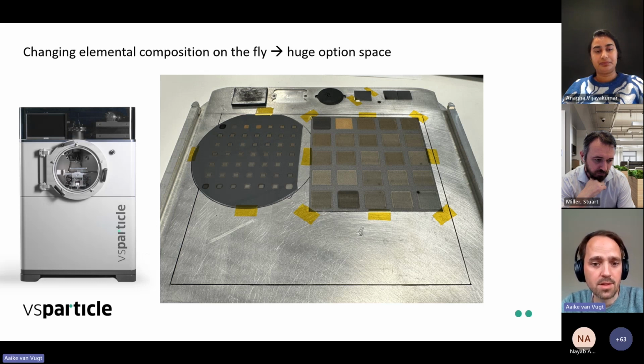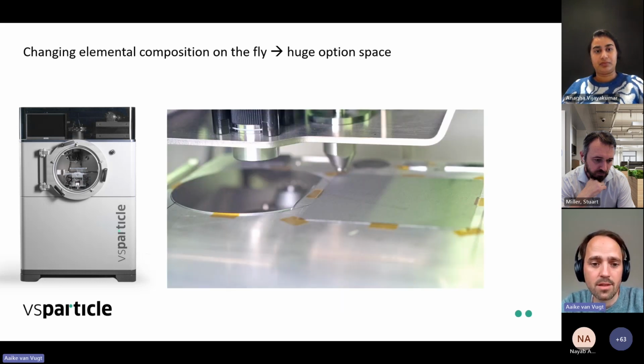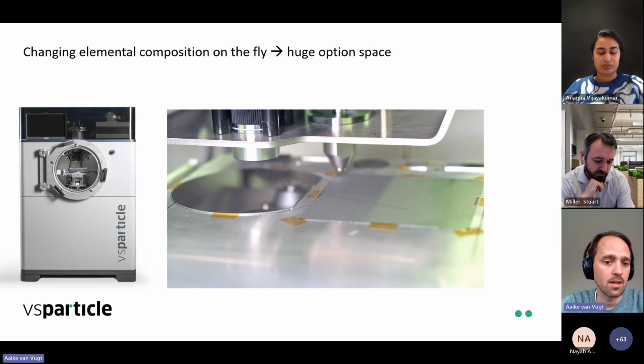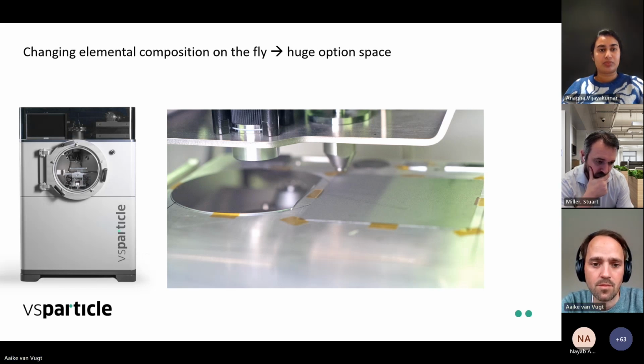And to give you a bit of perspective on how the system looks if it's printing these samples, we have a nice time-lapse movie made. So again, this is a system with two sources. Every source has a different material. We are printing fully automatically different compositions. So these prints could take 20 hours, 30 hours without any human interaction in between. There's just a single script. You set the system, you load it with the two different electrodes, you press the button, and then it takes 20 hours to print all those different material compositions. And then, yeah, you have your unique nanoporous materials that you can test. So this goes on for quite some time.